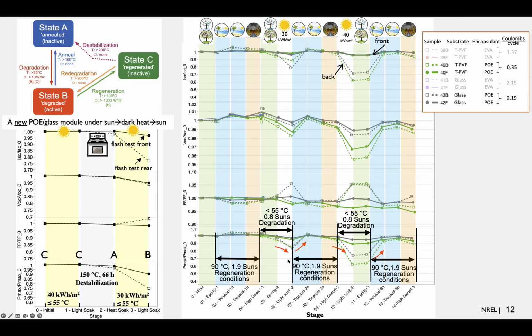And then what we also saw when we took it out of the chamber, in the spring sequence, is shown here. But we continued on with the tests, and when we moved back to the high temperature 90 and high light areas here, we saw regeneration again. The power recovered, and that's consistent with moving from state B to state C, where we're going at high temperature and light.